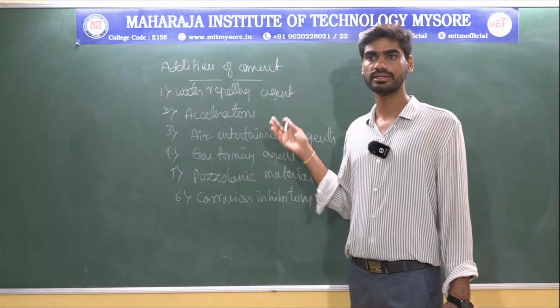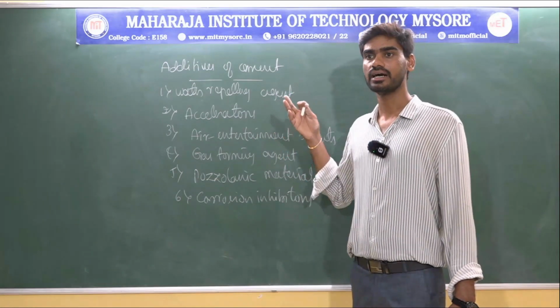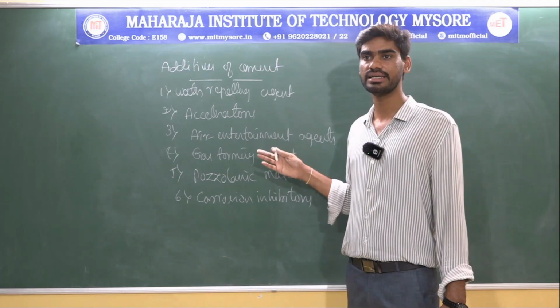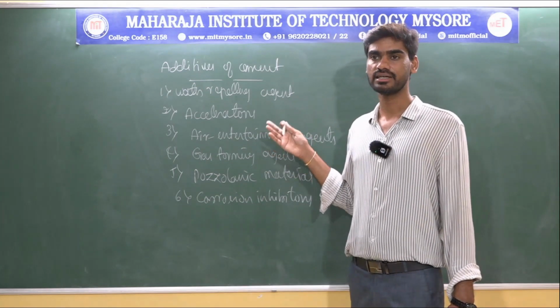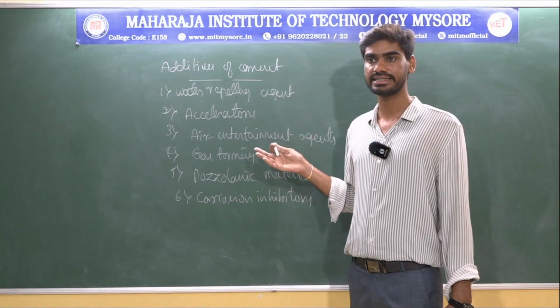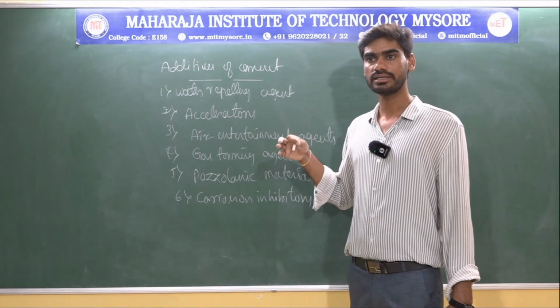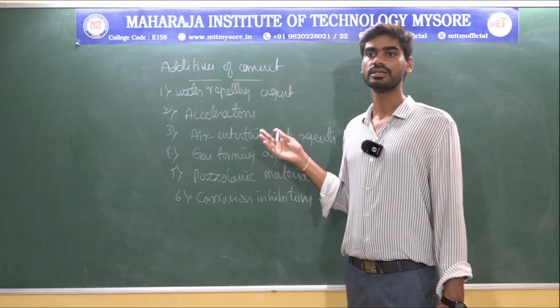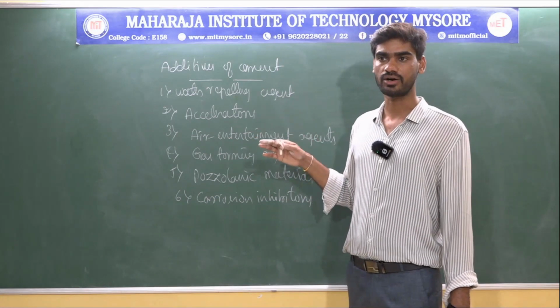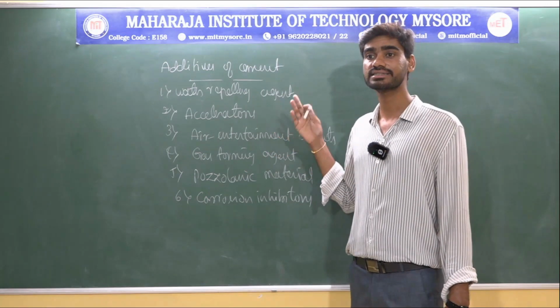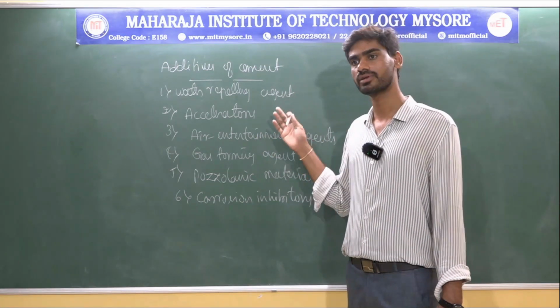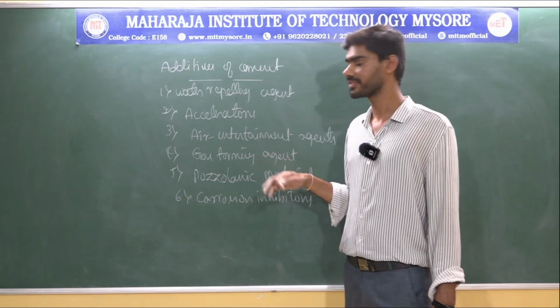Finely powdered siliceous and aluminous compounds are commonly employed, which are not cementitious, but when combined with hydrated lime and water give cementitious values. These compounds have minimal effect on the rate of gain of early strength, but provide higher strength to the structure under favorable curing conditions.